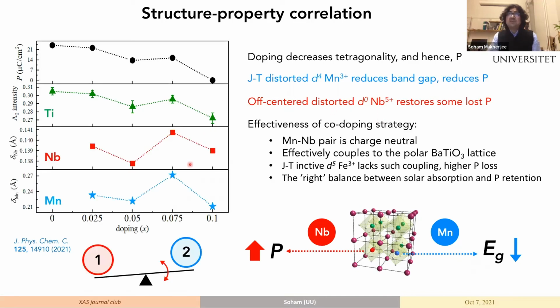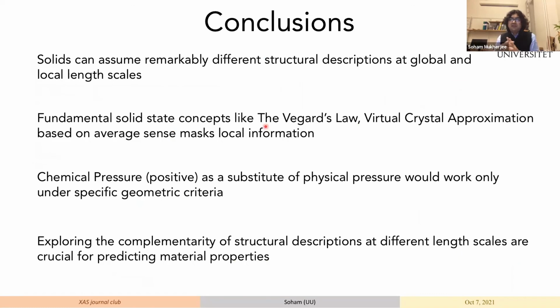And we also see that the absolute difference between the two distances, they also follow kind of similar trends, which means that these two together effectively couple to the lattice. And Jahn-Teller inactive iron 3+, which is a d5 system, lacks such coupling, and hence when manganese was replaced by iron, the system showed much higher loss of polarization. And with this, I'd like to conclude.